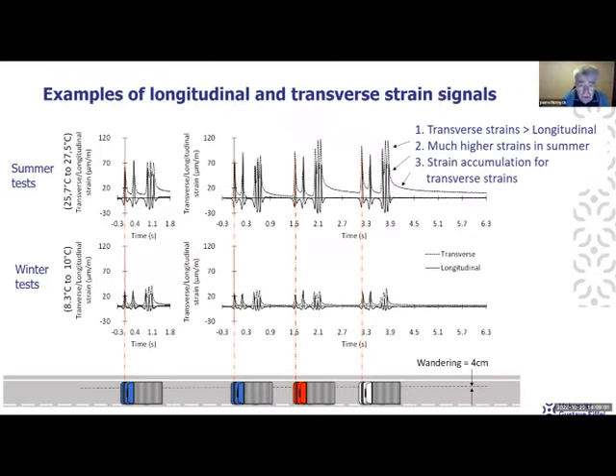And so we recorded a lot of strain signals under the passing of these different trucks. And so here you can see examples of longitudinal and transverse strain signals at the bottom of the base course in the winter and in the summer. And here you have an idea of the effect of the platoons. So first you can see that, of course, the strains are much higher in the summer than in the winter. And then you can see that in the summer, you have increasing strains under the second and the third truck of the platoon due to viscoelastic behavior of the material. And you have also delayed recovery after the passage of the trucks that you can see here.